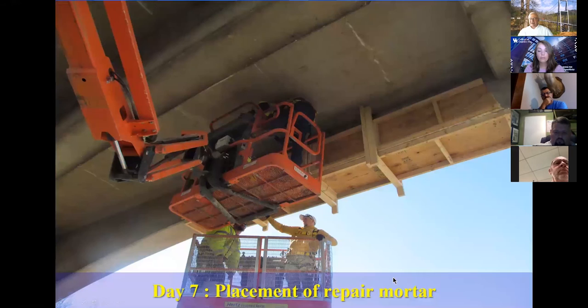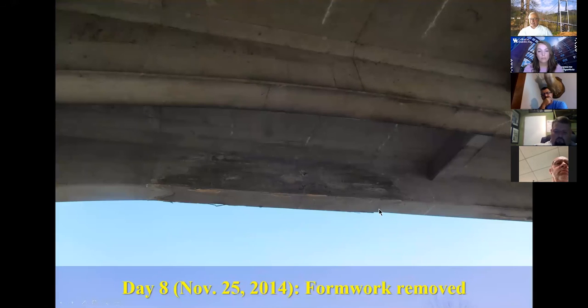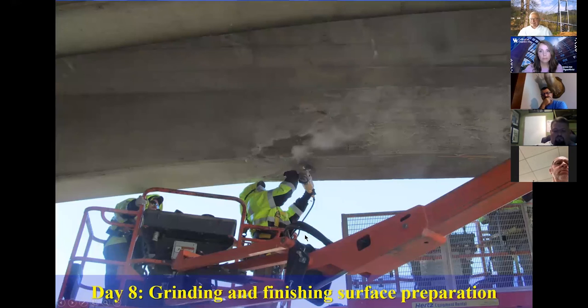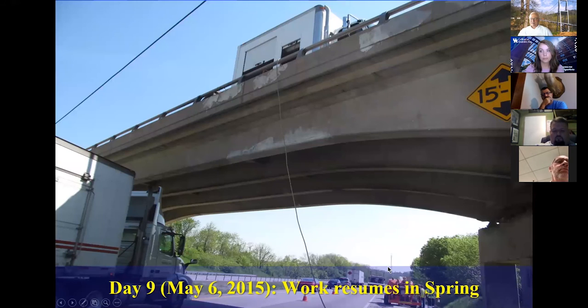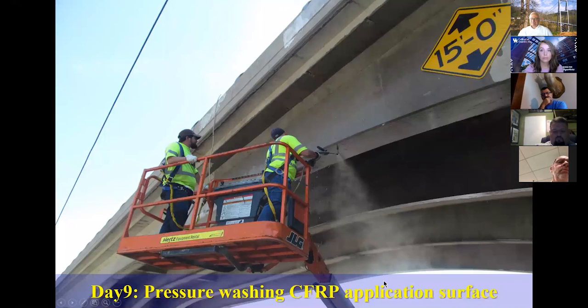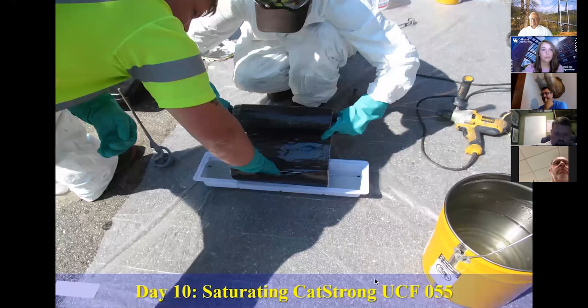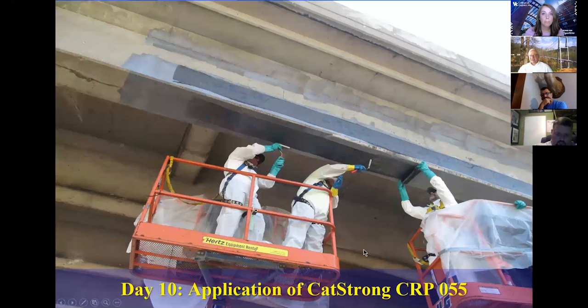We're mixing now the concrete to fill the form to bring the beam back to its original shape. And then we clean it up and sandblast it just like we did before. And then we start applying the fabric. The fabric is being doused in an epoxy resin, and then it's being placed.